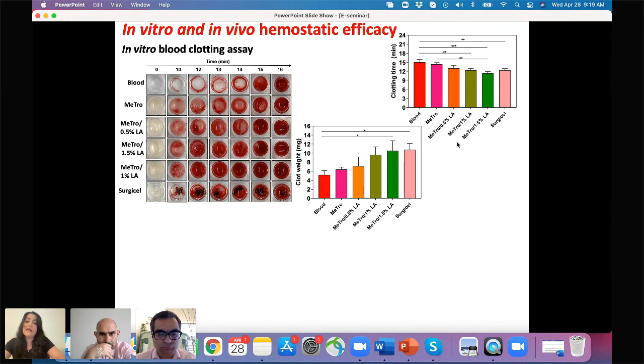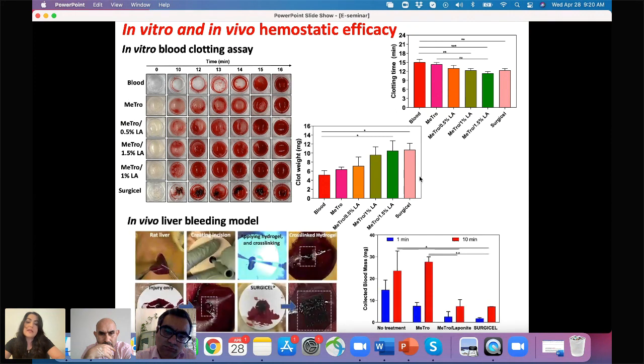And then here we show that as we incorporate laponite in Metro, we have a drop in clotting time, and it approached Surgicel. And we also have an increase in the weight of the clot that we collected. And for the Metro, for example, containing laponite concentration more than 1%, we had a clot mass similar to the Surgicel. So we then next move to our in vivo experiment. For the in vivo experiment, we use a liver bleeding model, and then we use our optimized formulation of a nanocomposite hydrogel, and our control was Surgicel.